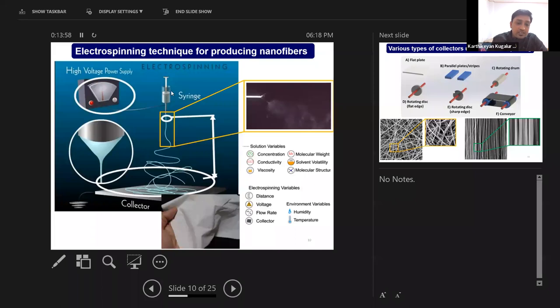So there will be a syringe. Basically, the polymer solution will be converted into nanofibers. The electrospinning technique is used to convert the polymer solution into nanofibers. When you are using the polymer solution, by using the syringe, you can pressurize it and it will flow through the needle. This needle is connected with a high voltage supply.